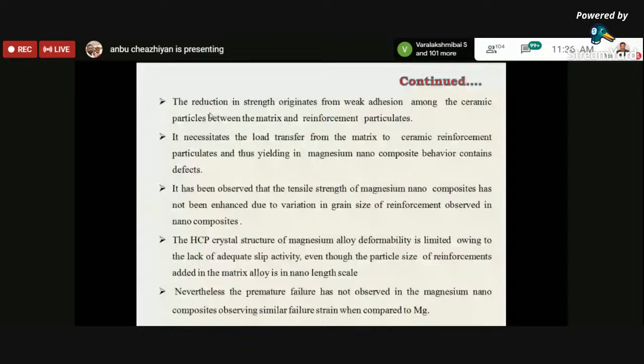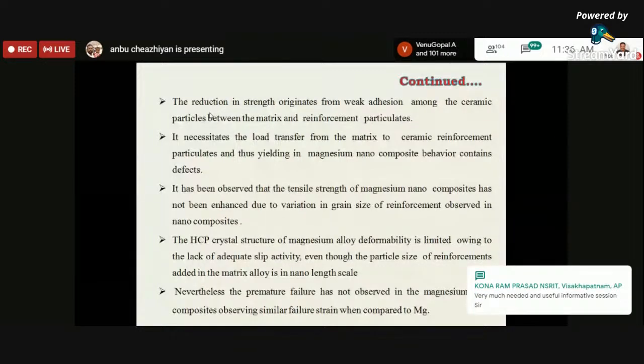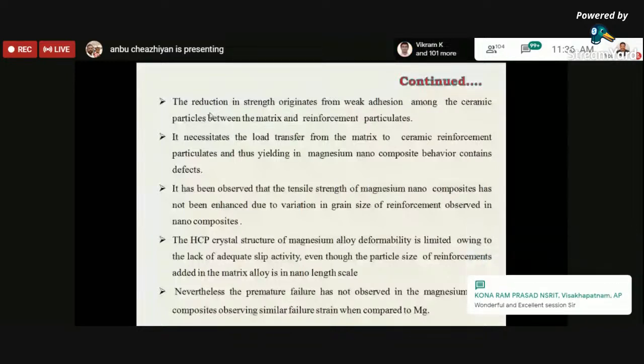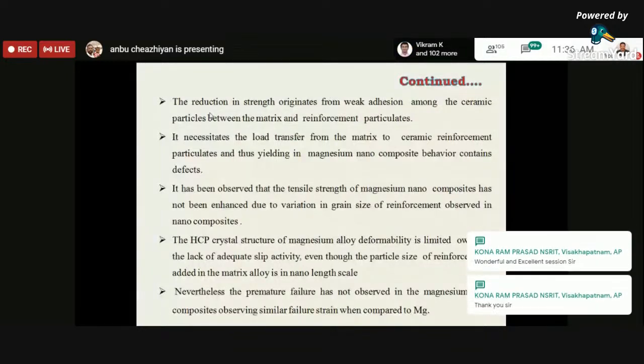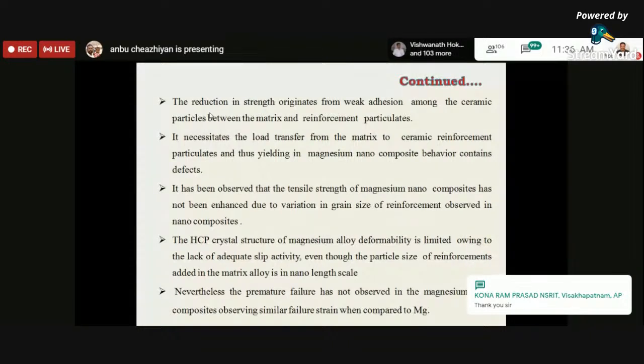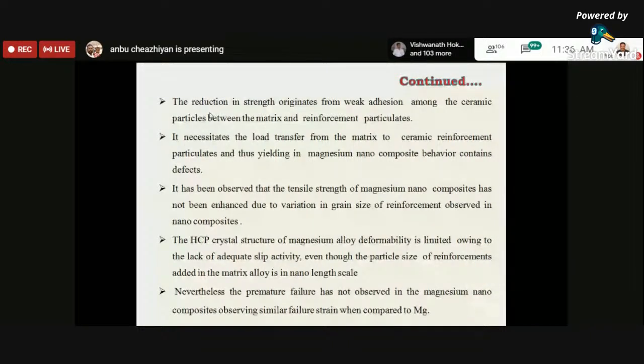It is also observed that the tensile strength of magnesium nanocomposites has not been enhanced due to variation in grain size of reinforcements observed in the nanocomposites. And since the HCP crystal of magnesium alloys has limited deformability, there is a lack of slip activity, even though the particle size of reinforcement added in the matrix alloy is nano length. Also, no premature failure has been observed in the magnesium composites.